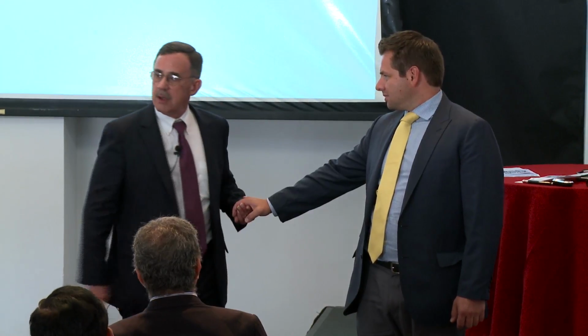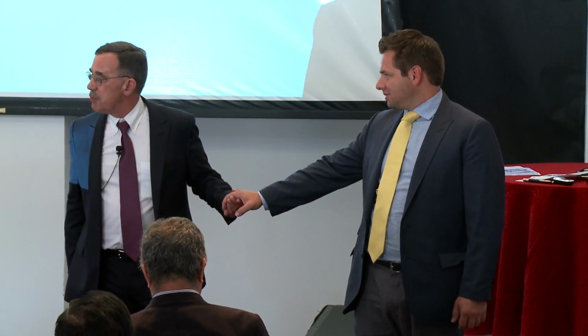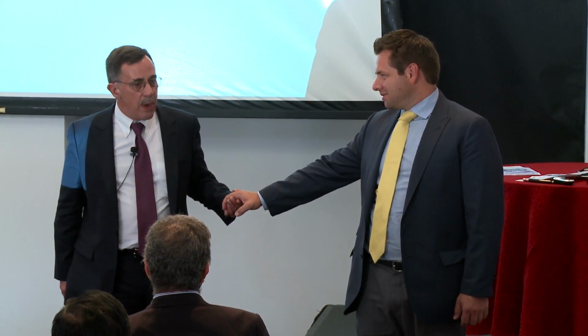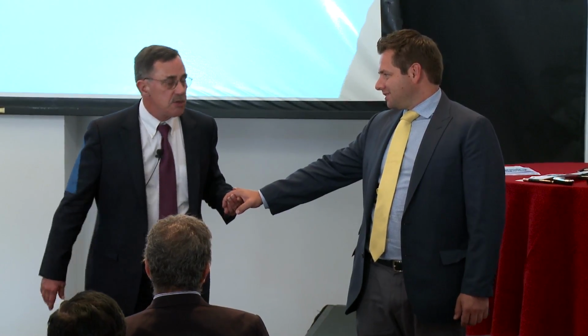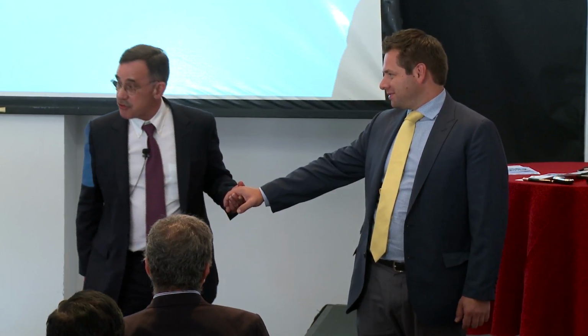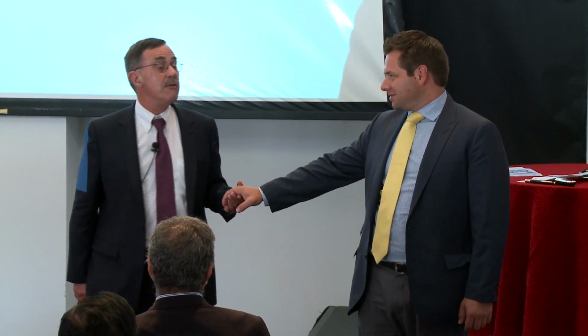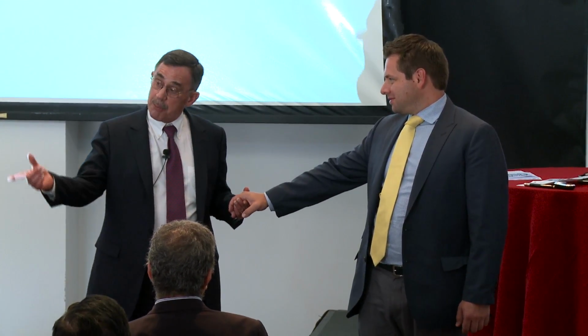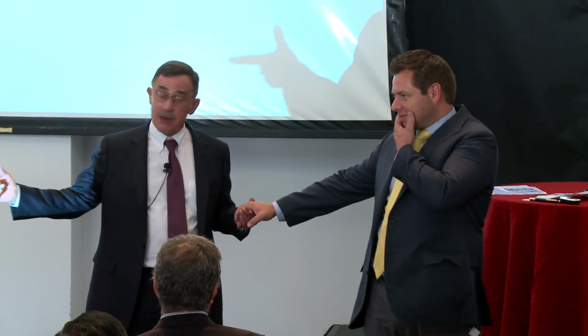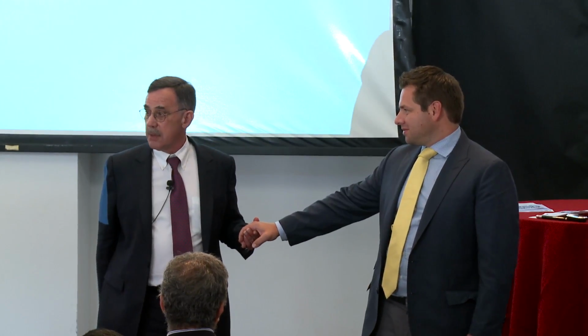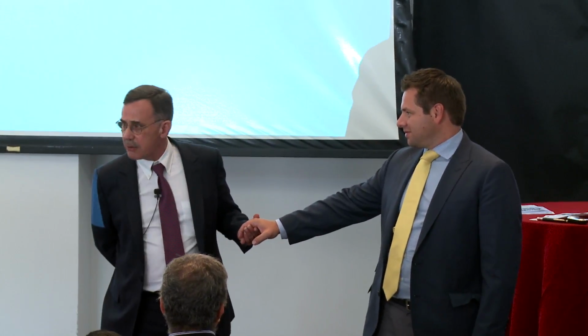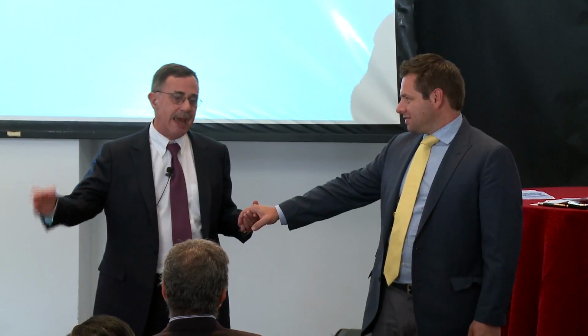So if chi and N are too small, enthalpy will win and we'll mix. So we can form a phase mixed structure or a phase separated structure depending upon the product of the segmental interactions and our size. And it has to be above a certain critical value. That value happens to be 10.5.